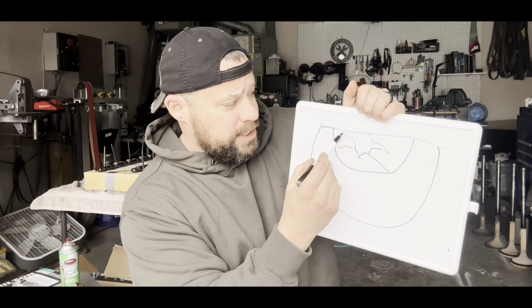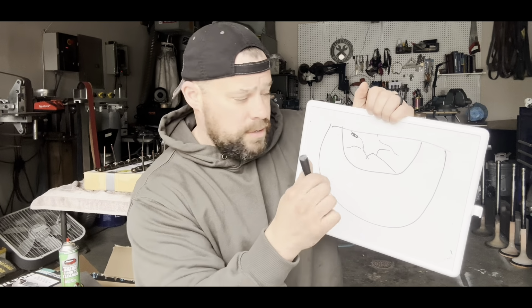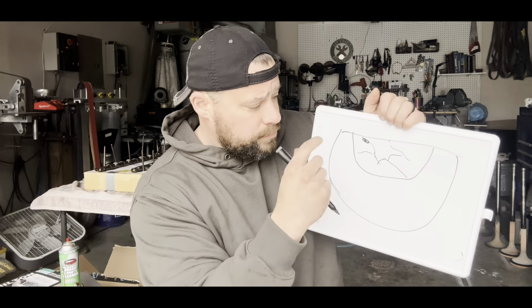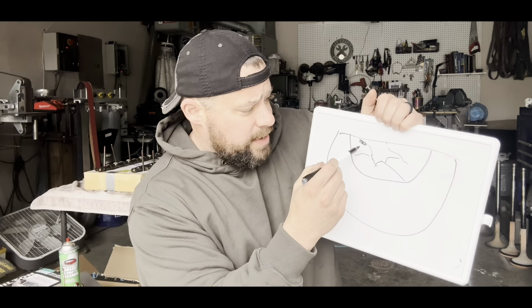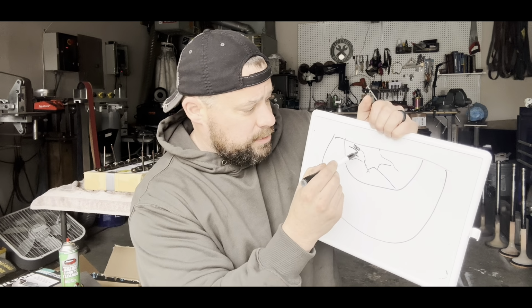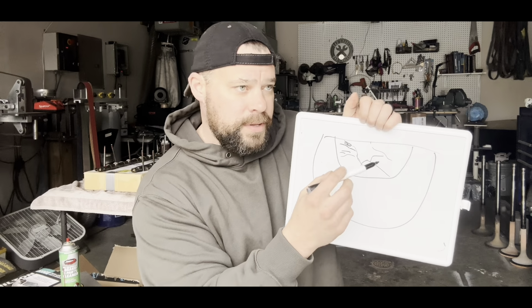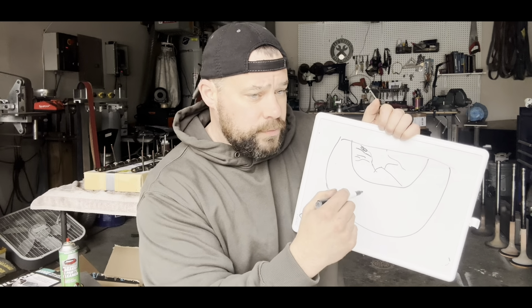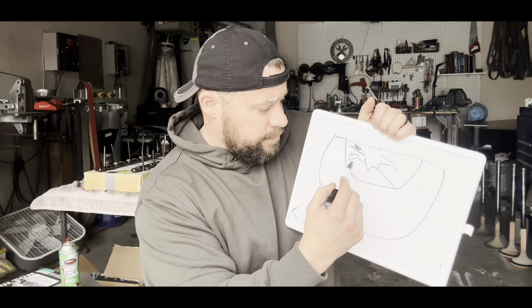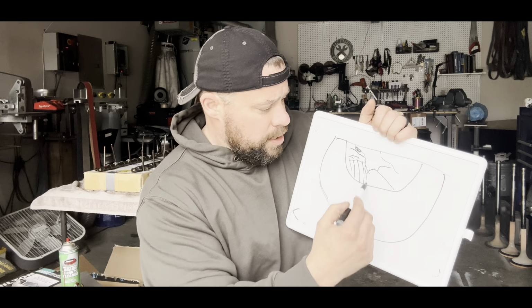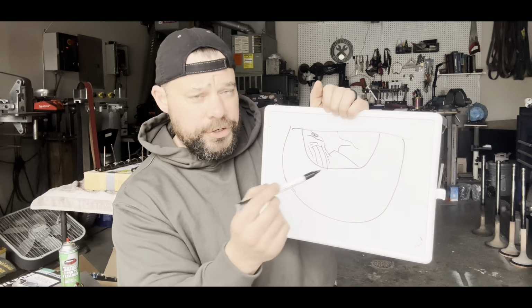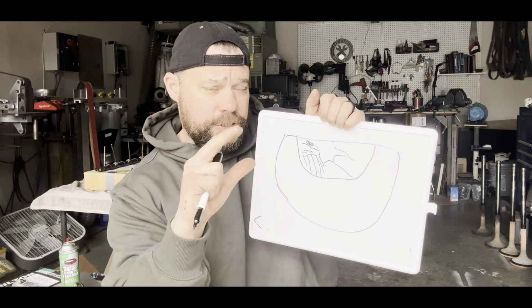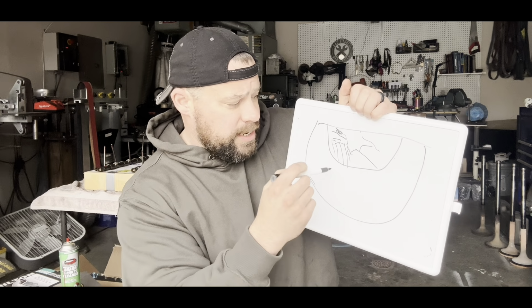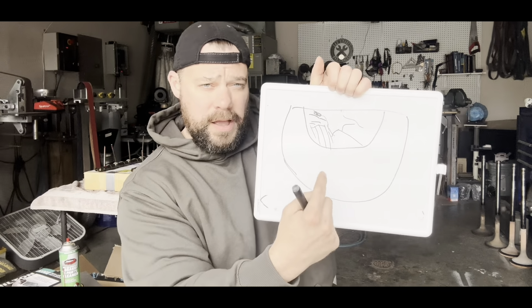When you look at them under the microscope, you really see all the coarse carbides on them. And then inside the grain, you get these needles, but you can also see some kind of grid pattern, somewhat of a dendritic structure. So when you're looking at that structure under the microscope, this is just looking at it with your naked eye.